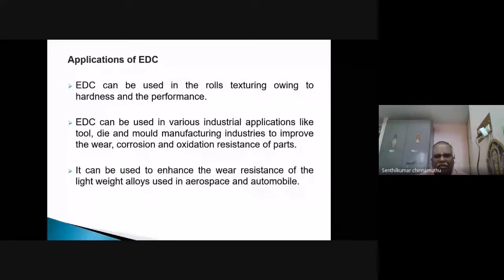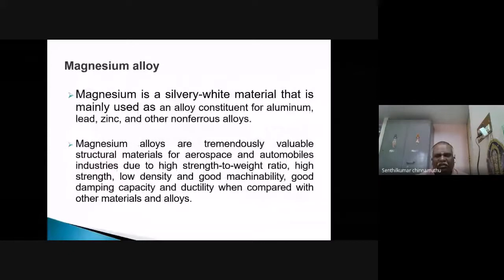Let us consider a magnesium alloy. In the case study, we select a magnesium alloy as a lightweight material and coat it with the help of tungsten carbide using electrical discharge coating. Why do we go for magnesium alloy? Nowadays, magnesium alloys are attracting the automobile and aerospace industries because of their light weight compared to aluminum. But the load carrying capacity and the wear resistance of this material are very low, so we go for electrical discharge coating.